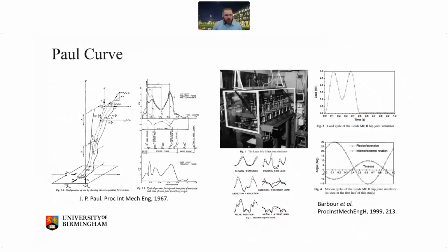So I mentioned there was some work done to look at the biomechanics in order to derive the joint contact forces at the hip, and this was referred to as the Paul curve, as early as 1967, where there was some force plate data that was then transferred through a biomechanical analysis in order to derive a contact profile of the forces that the device is essentially subjected to under articulation. What that analysis showed is that you would typically have a twin peak loading profile. So you would have an initial heel strike peak load, followed by a toe off load with an intermediate phase, and then a swing phase as your leg moves through to the next cycle.